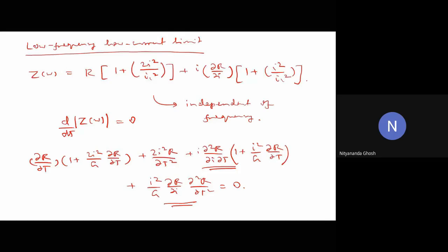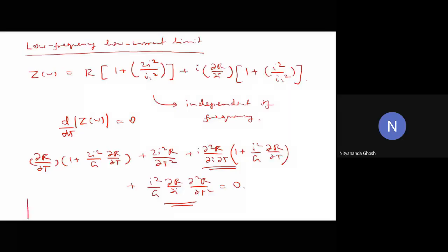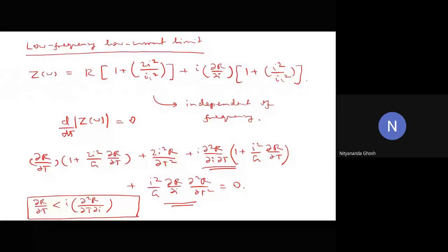So here it is important that the effect due to the transition is larger than the effect due to thermal effects like temperature, and that leads to a criterion, just by looking at the previous expression, which says dou R by dou T has to be less than I dou 2R by dou T dou I. So this is one of the criteria which is going to set the operation point for the bolometer in the low frequency, low current region. That is crucial here.